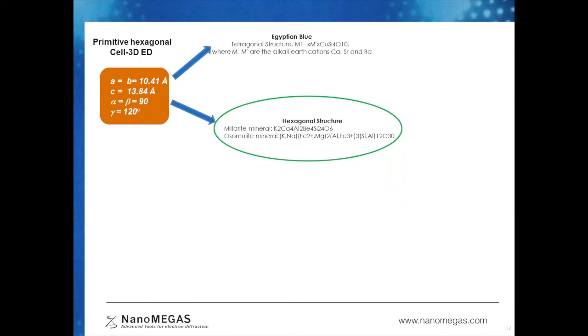In the next step, once we had the chemical information and the unit cell information, we looked into the structural database, especially from the ancient period, to understand which phase our phase belongs to. Then we found two possible options, two blue pigments found in the literature. One is Egyptian blue, and the other one is the mineral Milarite or Osumilite. But our structure is hexagonal, so we discarded the first one.